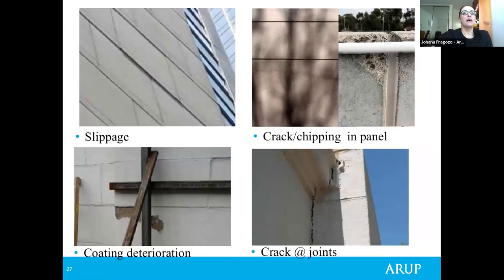In the next slide, you can see in the first photograph a slippage of facade elements of concrete panels, and this could be due to failure of the stone anchoring system or corrosion build up on the shelf angles or the use of inadequate anchor systems. By that I mean using of mild steel or coating steel that is not suitable for the environment where the facade is located.